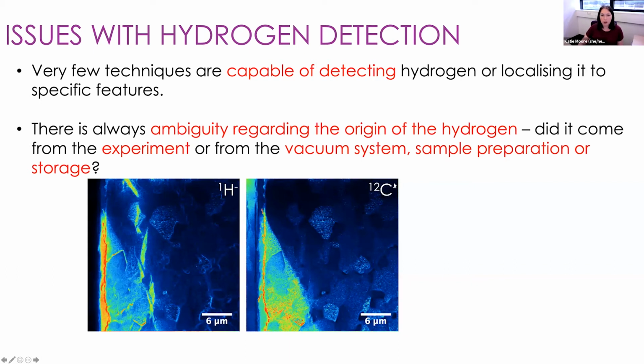So as we're imaging pixel by pixel from the top here, hydrocarbons from the resin have enough time to diffuse over the sample surface. And so these hydrocarbons, as they diffuse across, they're bringing in hydrogen with them. And as I said right at the start, this is a very surface sensitive technique. So we're imaging now those hydrocarbons on the surface rather than the underlying metal. So because of this issue with detecting hydrogen, what we actually do is we image deuterium, and we artificially enrich the amount of deuterium in our samples. And I will show you how we do that very shortly.